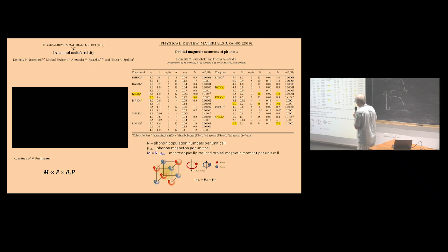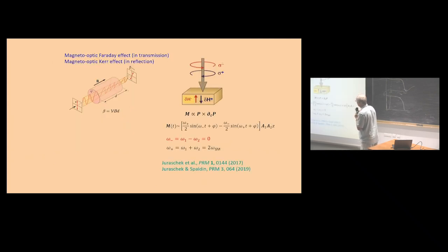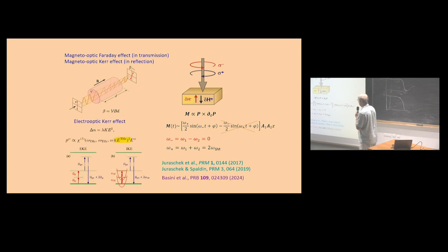This is the magnetic moment. It is a nuclear magnetic moment, not a Bohr magnetic moment. But in this case, I think it was overestimated because they took the phonon frequency quite high and so on. But anyway, I already showed here the magneto-optic Kerr effect. What is important is that using this pumping, the time dependence of magnetization generated by the circularly polarized beam should be like this, and because you have a doubly degenerate phonon, this omega minus should be 0. So finally, you can remove it, and you should expect magnetization if you do a Fourier transform. The magnetization should be at 0 frequency, so static magnetization, but transient, only on a picosecond time scale.